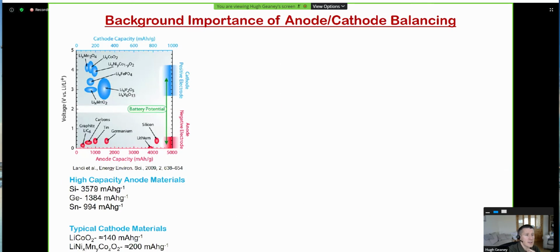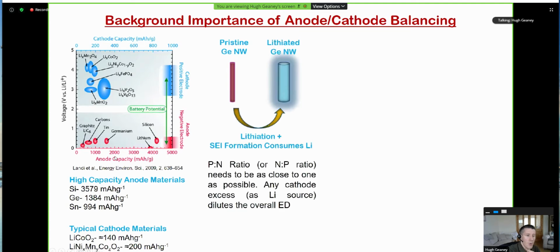So when we're looking at full cells, what's really important is the background importance in terms of anode and cathode balancing. If you look at the specific capacity of cathode materials, you see they're usually no higher than 300 milliamp hours per gram. But as we move to things like silicon and germanium, they're much, much higher. So they tend to be multiples of the cathode material. So what you can imagine is if you have a pristine germanium nanowire, you lithiate it, you will obviously expand it, but you'll form an SEI as well.